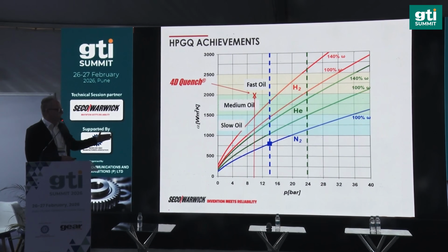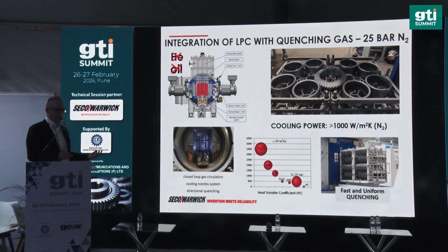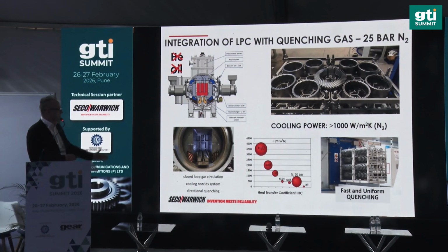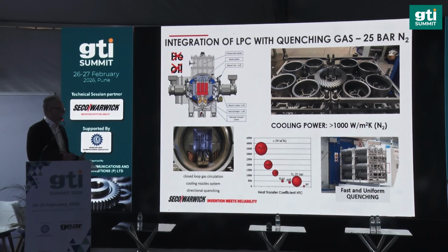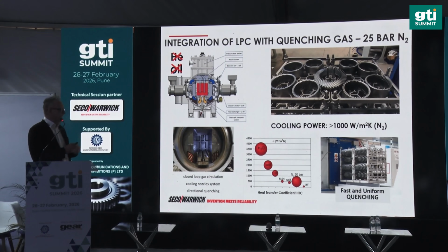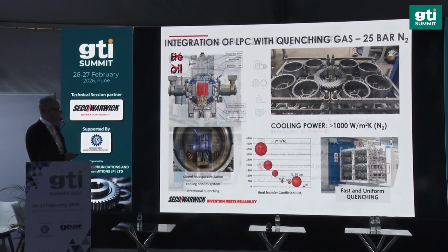So the message from this is that you cannot use high pressure gas quenching for any steels on the market, yeah? Even though you wish or dream to do it in order to decrease the distortion and the cost correlated to that, you might not. However, if you cannot do it, we also have a solution for that. Starting from high pressure gas quenching double chamber systems, which can, for the typical case, harden steels like 20MnCr5, 16MnCr5, 18CrNi7-6, this is a perfect solution, giving you the best benefits from the distortion perspective and the quality of the product after heat treatment.